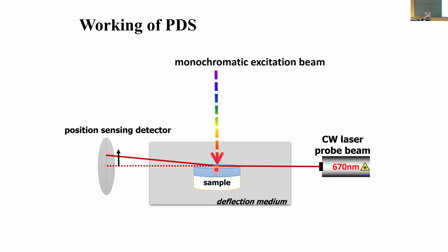So here we use that mirage and basically use a laser beam. This laser beam, nothing fancy, it passes on top of the sample where you have this heat. If you have a heat difference, you have a refractive index difference, and the beam will deviate. If you don't have any absorption, it doesn't result in any heating. The delta T is zero, so the laser goes straight through.